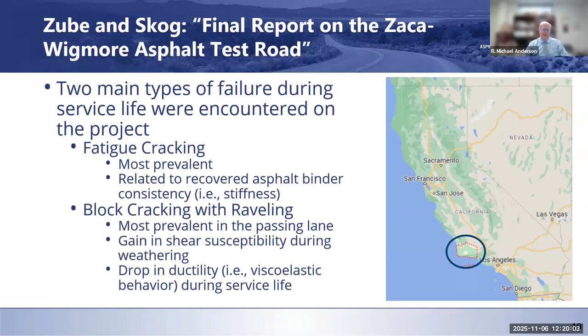The other part of that was not something that was directly addressed, I'll say, but it was recognized, and that's that they also had block cracking with raveling. And that was more prevalent in the passing lane. So fatigue cracking happened in the driving lane, where you would expect it. That's where the traffic loading was. But in the passing lane, where you didn't expect much traffic, what they saw was block cracking with raveling that was due to a gain in shear susceptibility during weathering. In other words, it aged, yet lost its ductility during that aging, and so it lost its viscoelastic behavior, and they ended up with some block cracking that occurred.